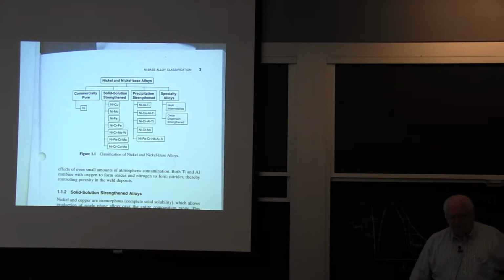I went off in 1984 to Tokyo for the Navy, came back afterwards and said, well, what happened? Have you patented it? And they said, well, we decided there wasn't a real application for it. I said, oh. So they said, well, but can you make us age hardenable sterling silver? So I went and tried the same thing with sterling silver. First attempt was a failure. The second attempt, sterling silver is silver copper alloys. Second attempt, I added lithium and tin, and it worked. And the lithium and tin worked. Same type of principle. Lithium and tin form a high temperature intermetallic. They both dissolve in silver.